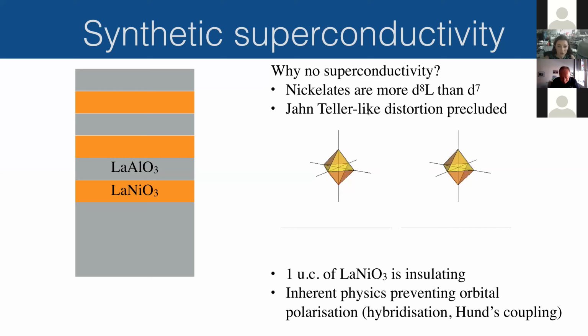The Jahn-Teller-like distortion, this compression of the octahedron, might be precluded. So a pure Jahn-Teller distortion would be like this, where you just have changes of the bond lengths. But instead what we have is more like this one. So you might have, instead of changes of bond length, just rotations of the oxygen octahedron. Also, 1 unit cell of lanthanum nickelate is insulating. It's not metallic, which is what was assumed when this type of structure was proposed. And there might be something inherent in the physics of nickelates that wants to prevent orbital polarization. So I'm going to just go into a bit more detail on this point, and this point. So the last 3 points.